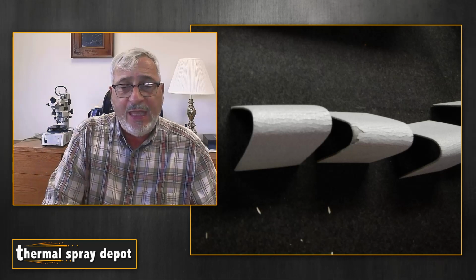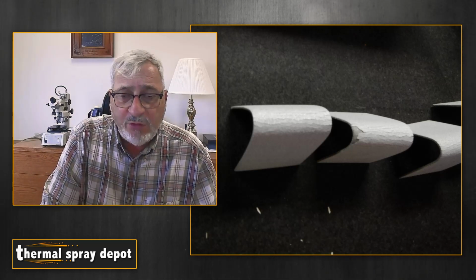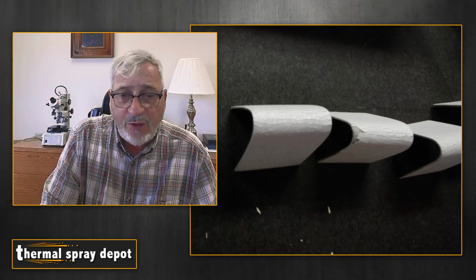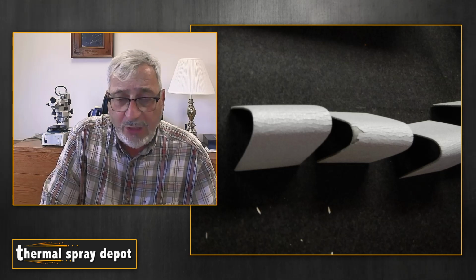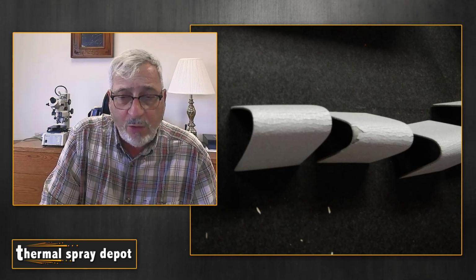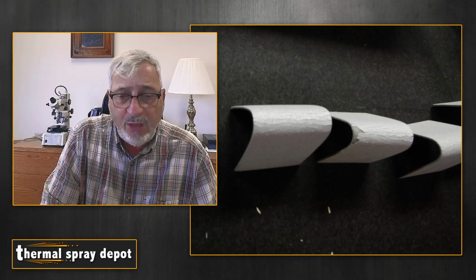We did this again as a demonstration with operators when we were doing training, to show that if you do everything exactly right, you can get some pretty great results on these coatings, being able to bend around pretty stringent radiuses. And now let's go back to the girder example. If you had a girder that bent that far, you've got far more serious problems than worrying about the coating popping off. The girder already failed. Yes, absolutely. So in this case, that's not going to be a big issue.